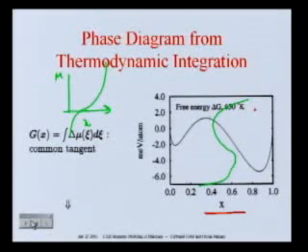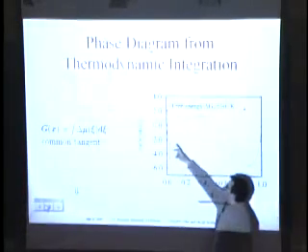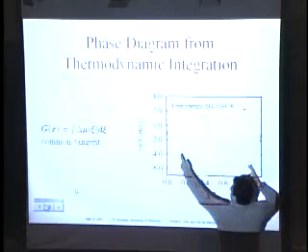But this is good, because when you invert this and you integrate, what you see is that for your free energy as a function of the concentration, what you would really obtain is real free energies only from 0 to 0.1, or from 1 down to something like 0.8, 0.85. And in the middle, you have this famous miscibility gap, in which really the free energy of the solid solution is higher than the free energy of the end compounds. And so you have the Maxwell rule and the tangent. And so what you have is the composition of your system.